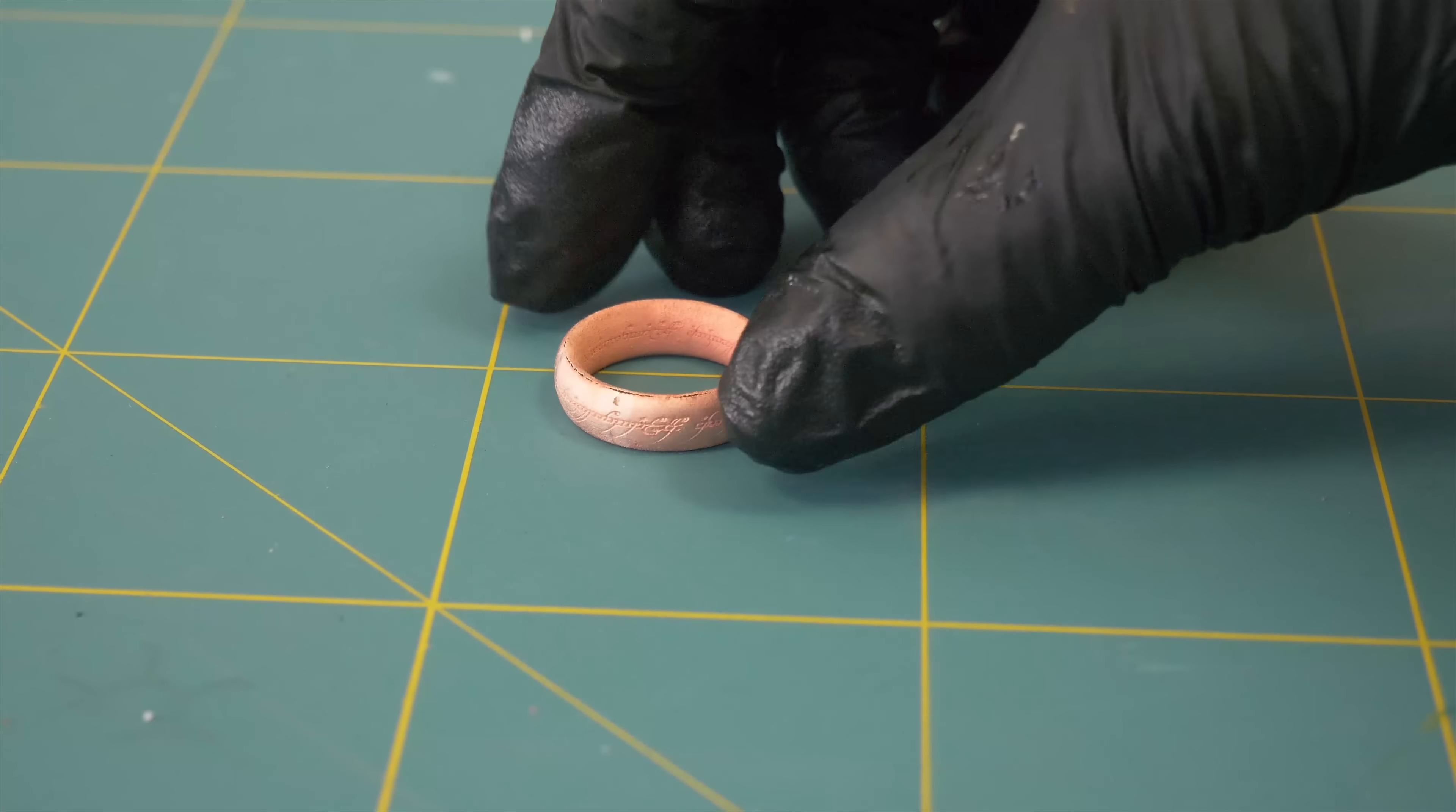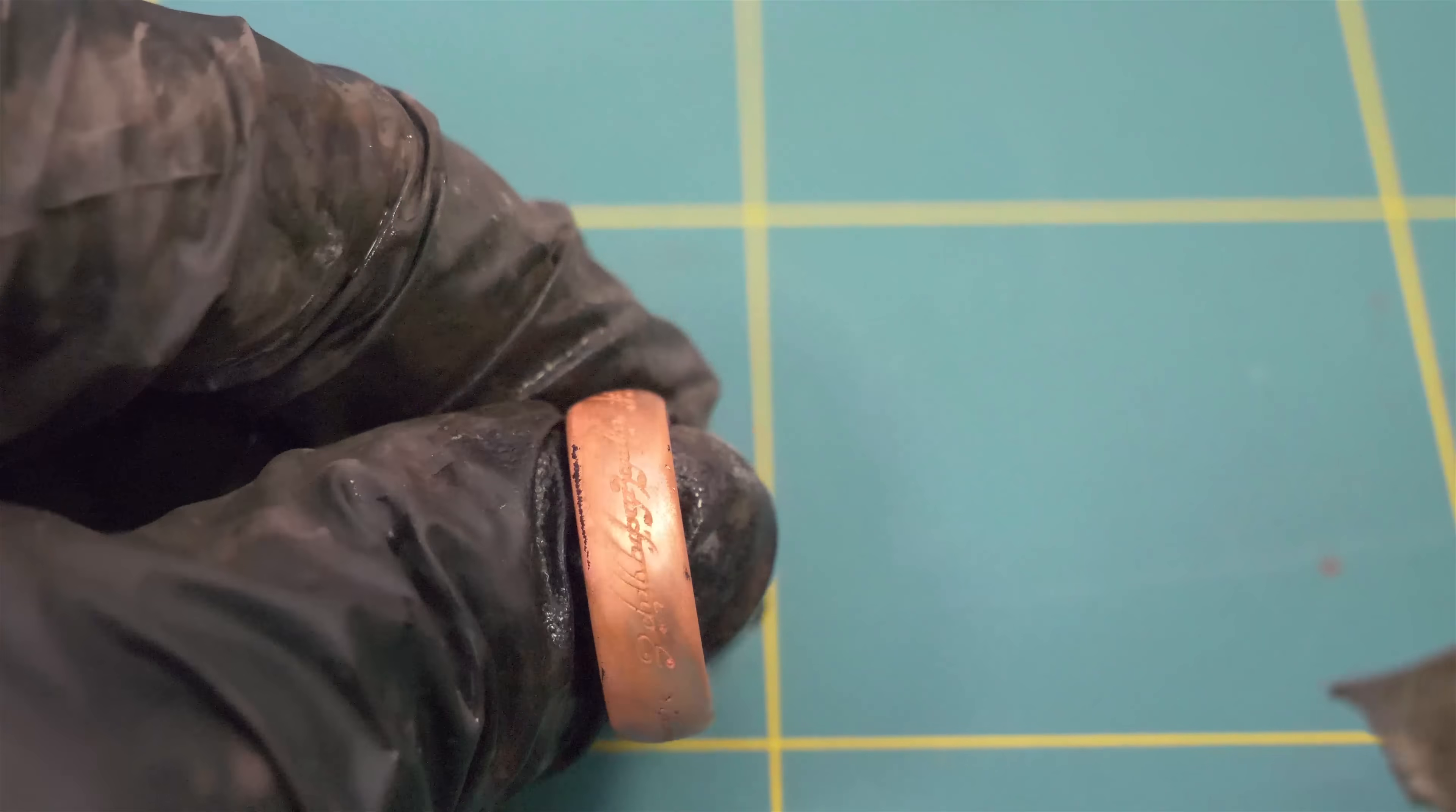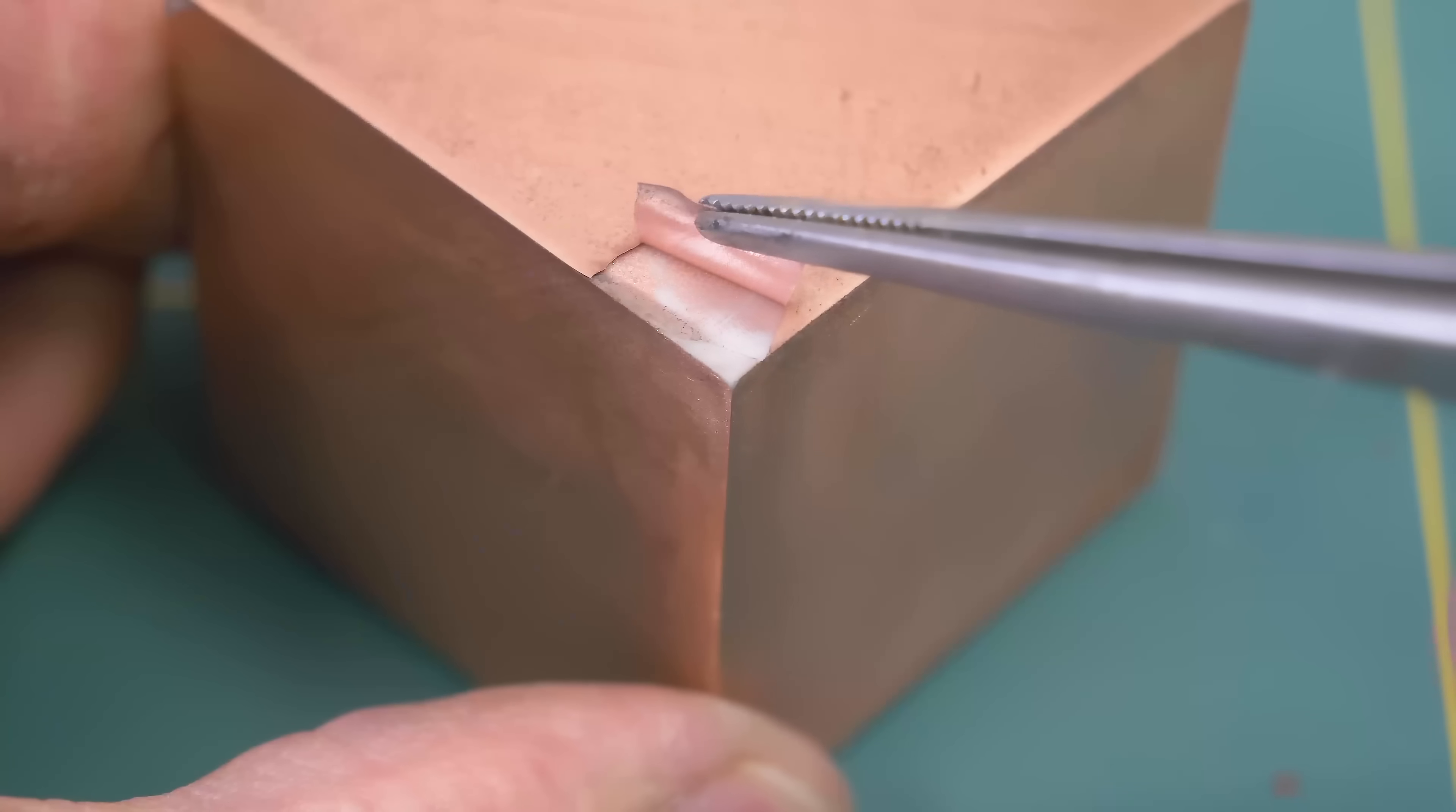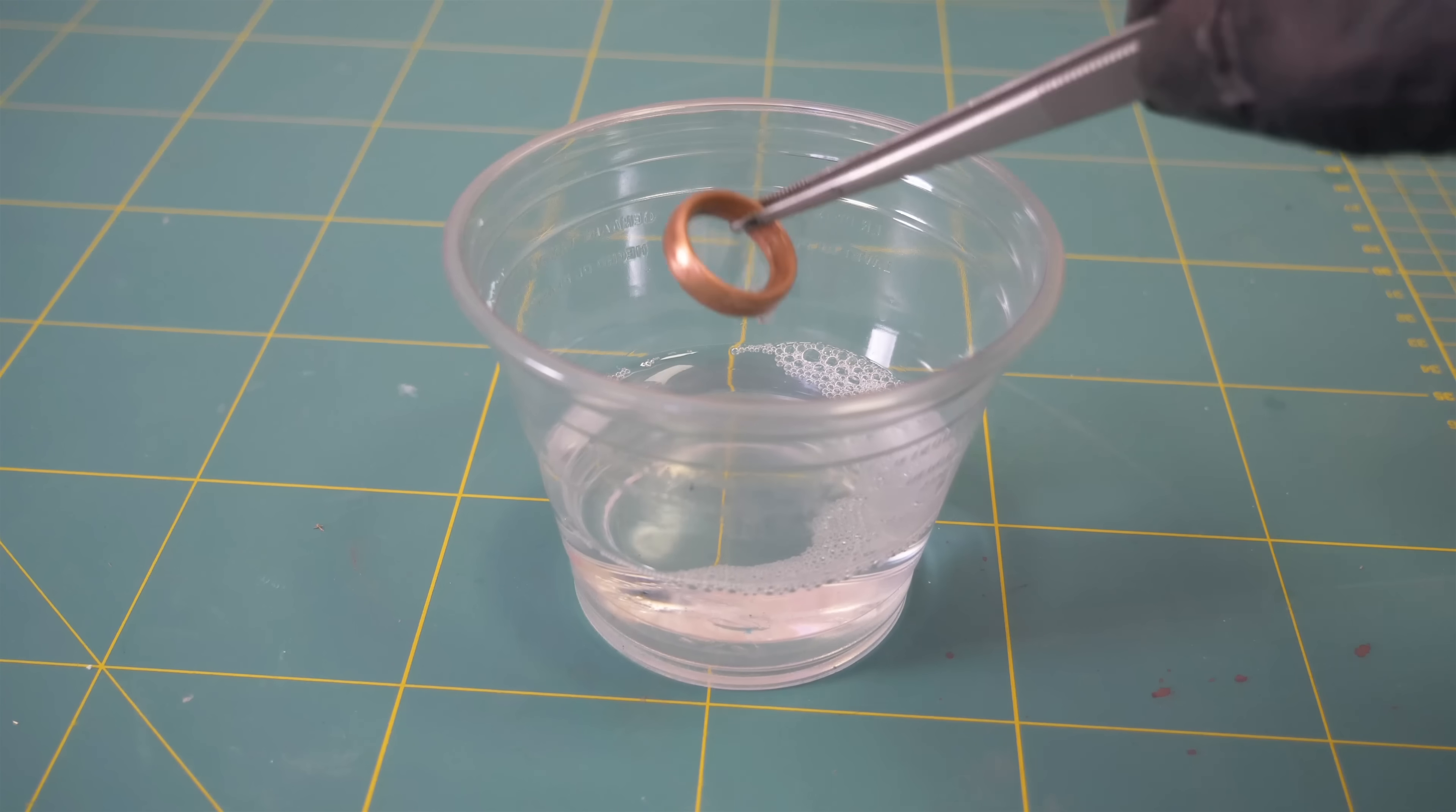If the surface is rough, you may try to carefully polish it with fine grit sandpaper and polishing paste. But be careful, sanding it too hard may damage the layer. When this is done, degrease it again and continue with other metal layers.